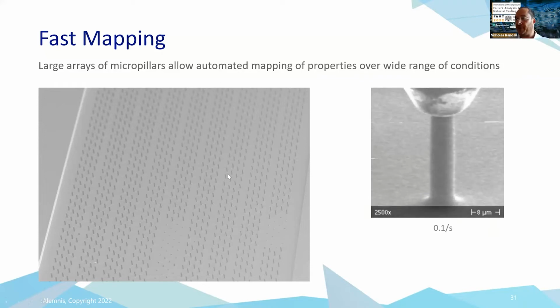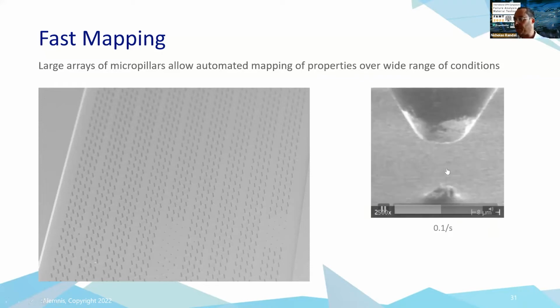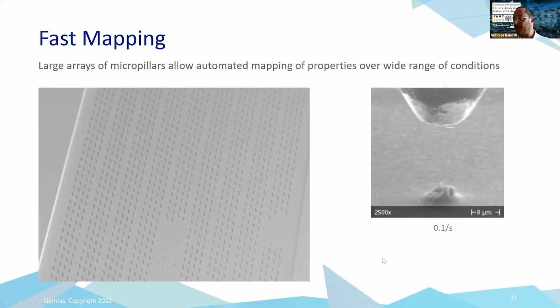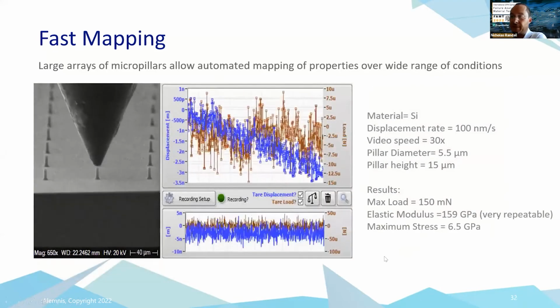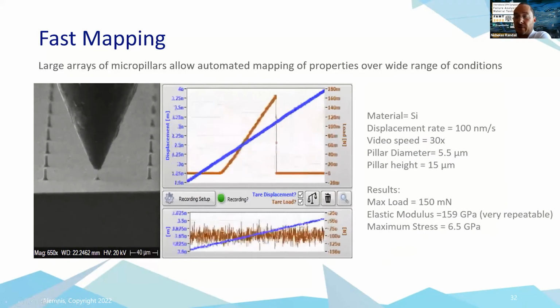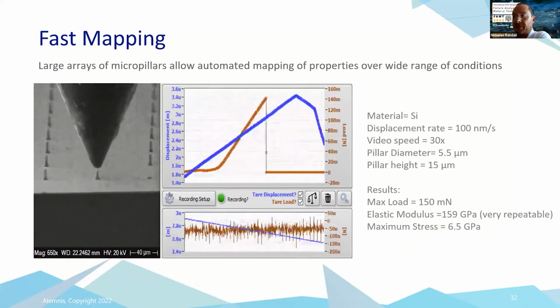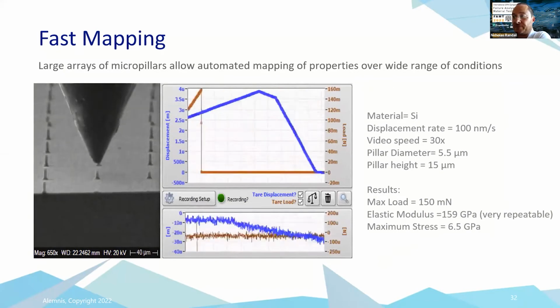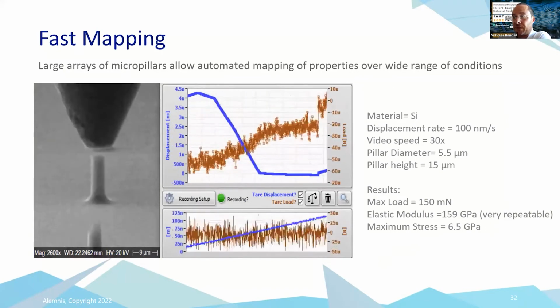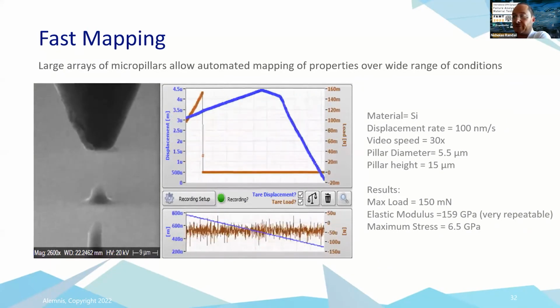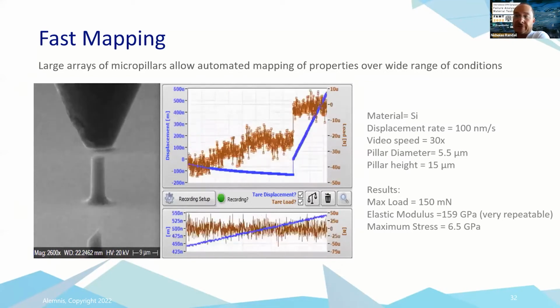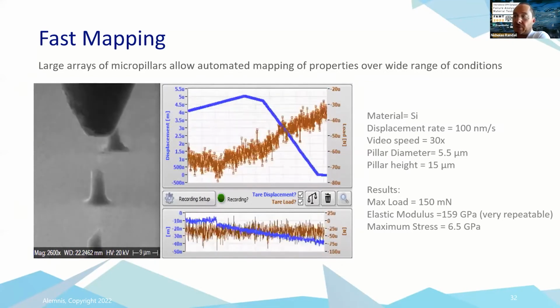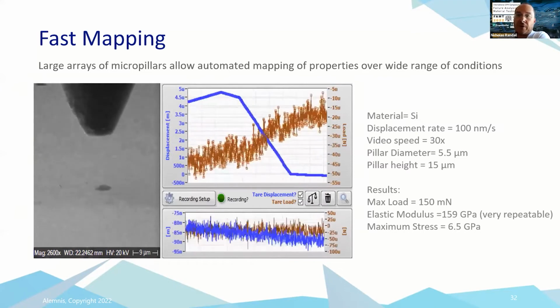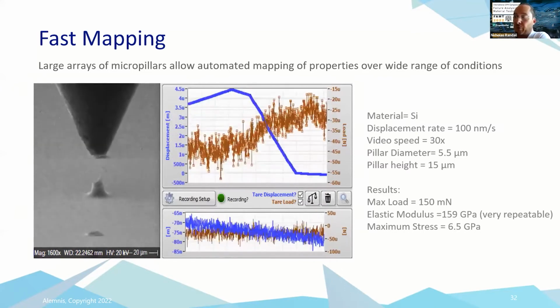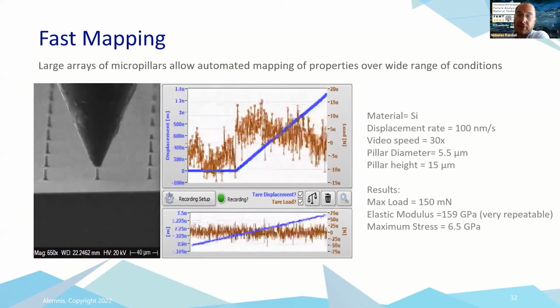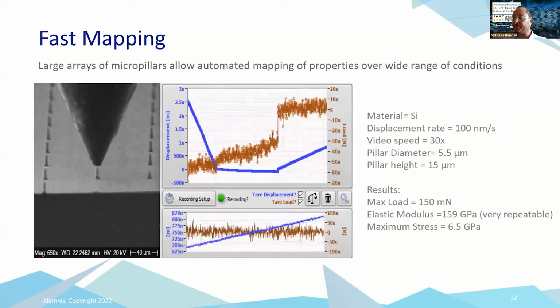So this is an array of silicon pillars. You can see one being failed on the right here. And here you can see an automated test where we're basically going to every pillar and testing each pillar with slightly different parameters. So you could have some pillars, for example, on different areas of your wafer around devices. And as a quality control tool, you could be testing those pillars just to be sure that the material or the coating hasn't changed in properties and you don't have a production issue.